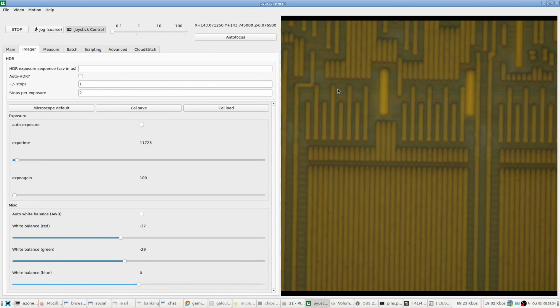One interesting thing about this particular process is that the vias actually have slightly larger annular rings on the ends of the tracks. On most modern nodes, the vias are the same diameter of the track or even slightly smaller, and so you can't actually see a via from the top in an optical image because it's the same width as a normal track. You can often see some higher backscatter yield in SEM, especially on aluminum process where you've got a low Z aluminum conductor and then a high Z tungsten via plug under it. But in optical, obviously, you don't get backscatter contrast, so you don't have any of that information.